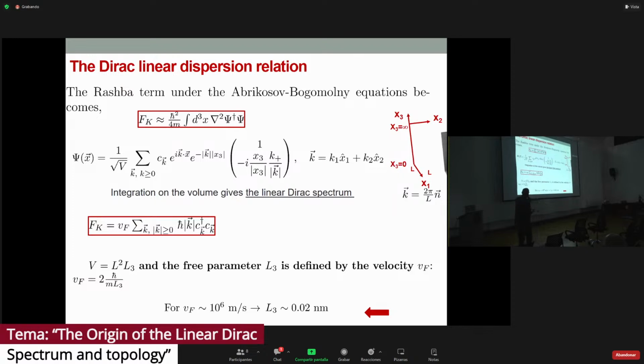And once you do all these approximations, I mean, all these considerations, the kinetic energy is just that. Here you see a 3-dimensional version. This is the Rashba term added to the first order equations. This is nothing but a surface term because it reduces to integration in this surface. If I put my solution for the order parameter, which is exponential in the 3rd direction and propagates along the plane, with arbitrary coefficients, I found this kinetic energy is essentially H modulus of K times this product here, and I interpret these C's as creation and annihilation operators for these quasi-particles.